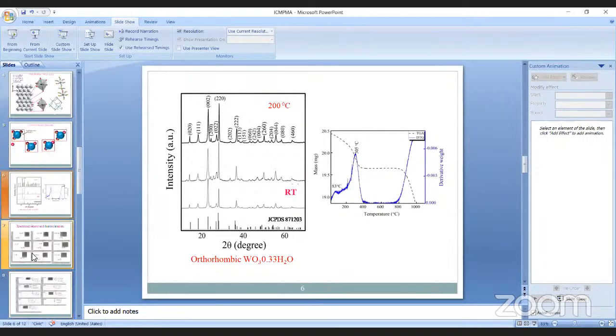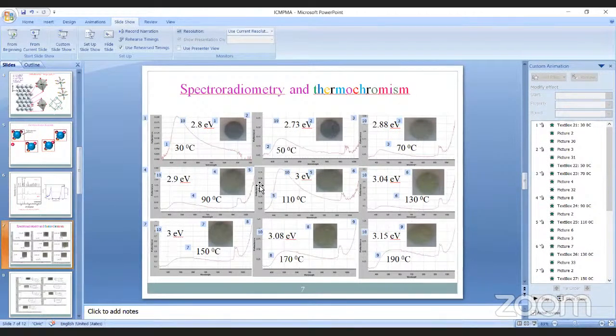Now, we are interested in the chromogenic properties of this material. Thermochromism means simply the color change in the material when the temperature stimulus is given. To study the thermochromic property of the material, throughout the study we kept the sample on a hot plate and applied the temperature. For different temperatures, we take the reflectance of the sample with respect to wavelength, and at different temperatures we take a photograph of the sample, which is also shown in the inset. Clearly from the inset, we can identify the color change of this material from 30 to 190 degrees Celsius.